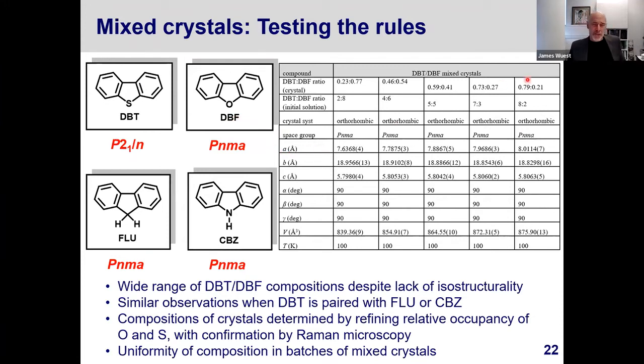So these compositions, there are lots of things about mixed crystals that you could ask. I mean, one is that in a given batch of crystals, there were small variations from crystal to crystal, but by and large, the composition of the crystals reflected the feedstock that was used, and the composition of the crystals remained constant. We did this by selecting various crystals and examining unit cell parameters, in some cases solving the crystal structures.